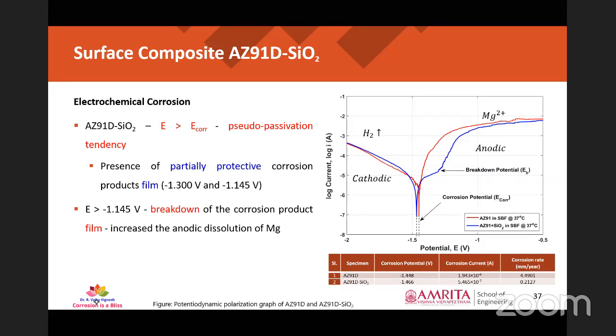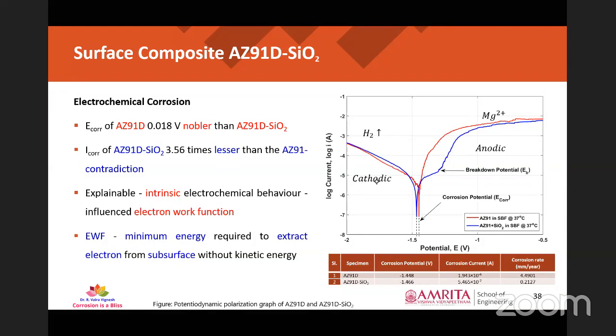Okay, and this pseudo passivation tendency is lacking in the base material, and in the case of the composite we have a pseudo passivation tendency. That means that there is an adherent layer of corrosion products that is forming on the material. Okay, and when we speak about the corrosion potential of the materials, the as-received base material AZ91D had a corrosion potential of minus 1.448 volt, and the composite had a corrosion potential of minus 1.466 volt. So it means AZ91D is nobler than the composite material, but the corrosion rate, which is determined by the corrosion current, is 3.56 times lesser than that of AZ91D, which is a contradicting result.